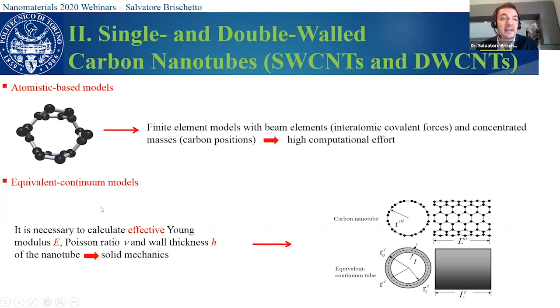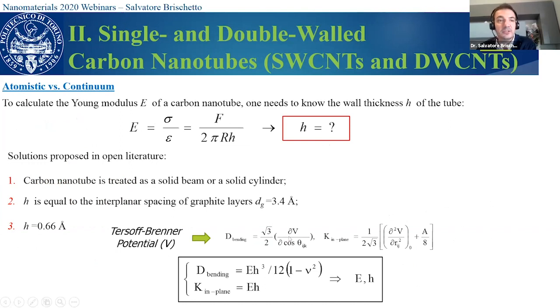A third possibility is equivalent continuum models, because a carbon nanotube is a discrete model, and we consider an equivalent continuum tube where we suppose a hypothetic thickness. Obviously, the problem here is to define appropriately the Young modulus, the Poisson ratio, and the wall thickness h. There are several possibilities in the literature in order to solve this problem, that is atomistic approach versus continuum approach. So in order to obtain a Young modulus which could be quite correct, we must define this hypothetic thickness, and it is not so easy.